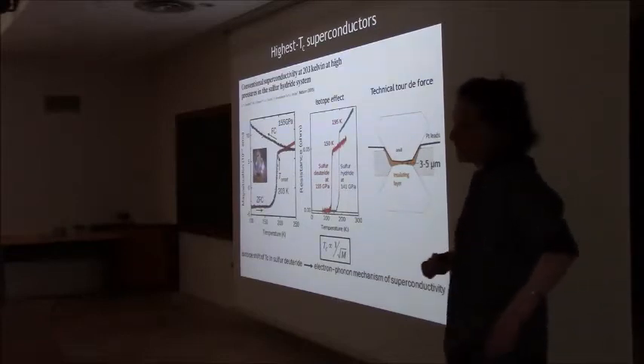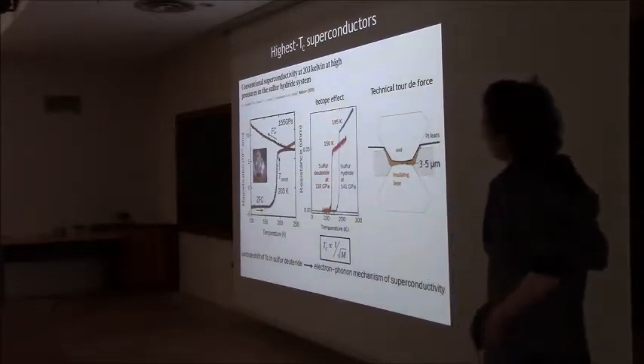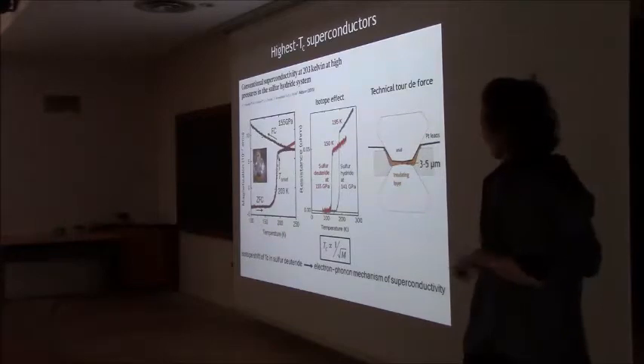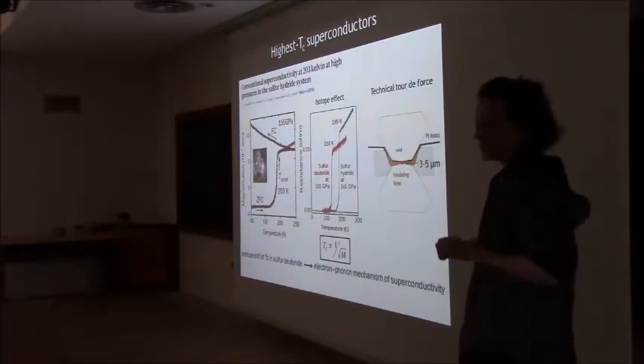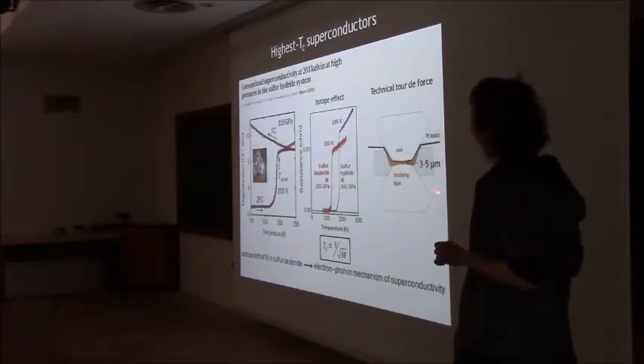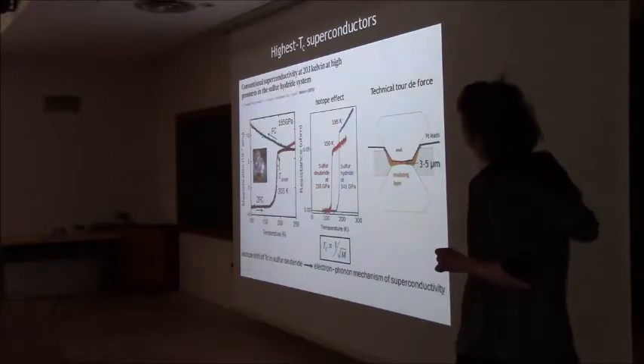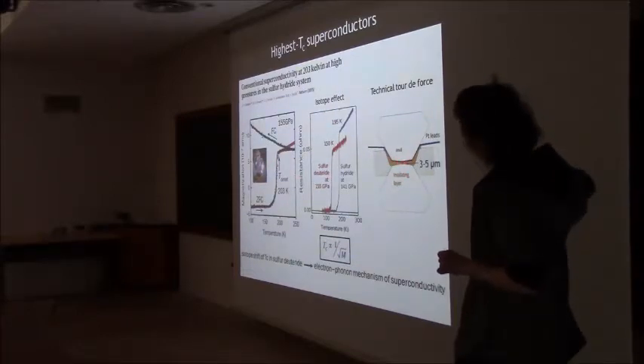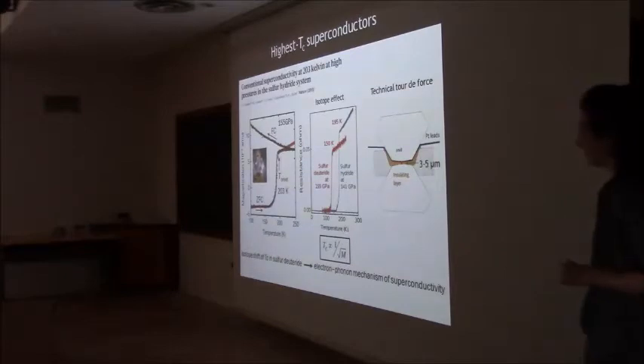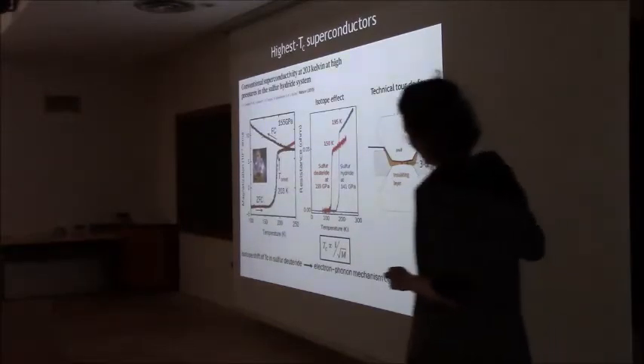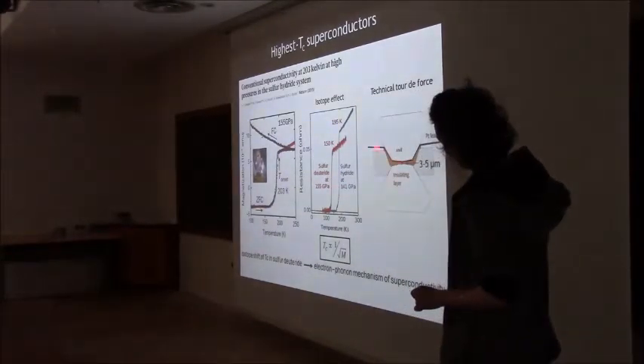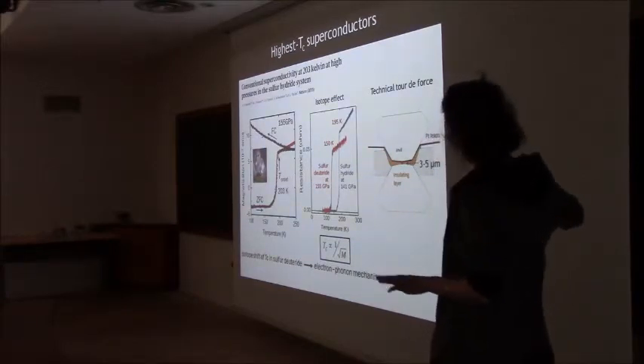So they use a diamond anvil cell for that, with a very, very small culet, maybe about 30 micrometers. And the thickness of the sample is between 3 and 5 micrometers. It's an extremely difficult measurement. And they were also able to measure resistivity under this high pressure.